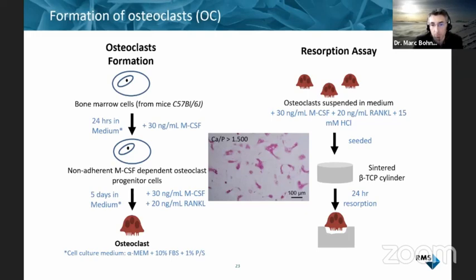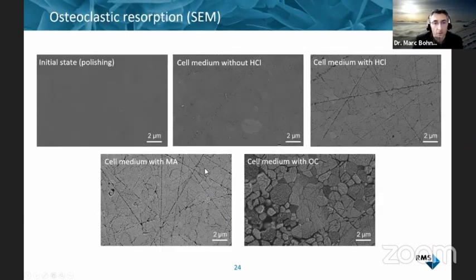This is just an image of the TRAP positive cells present on the surface, where you see that they are clearly TRAP positive and multinucleated. The surface of the sample looked like this before the cell culture test. You see some of the polishing lines. If you place it in the cell culture medium, you see a tiny little bit of dissolution. Mostly we attribute this to the formation of an amorphous phase on the surface, especially in the polishing lines. The osteoclast resorption is activated by adding a bit of HCl that lowers the pH to about 7.1, and we can see that this affects the surface a little bit, dissolving it a tiny little bit. If you add macrophages, nothing really happens, and if you add the osteoclasts, you start seeing resorptive activity, with needle-like structures and the formation of pits.